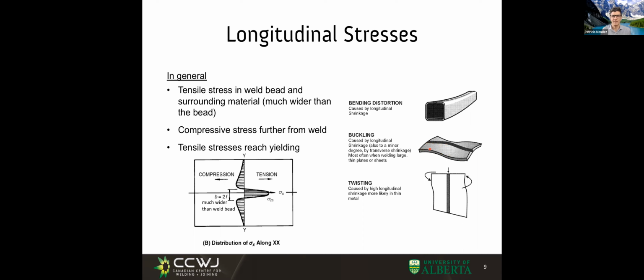Another thing that is seen, which actually is a form of buckling, is twisting. So along this length, the length along the bead gets shorter because of the shrinkage stresses, and the other parts that were farther from the bead never changed temperature, so those never got shorter. And the way they relieve the stress is by twisting. So while this goes straight and is shorter, these sides are now diagonal and make a shorter effective length.